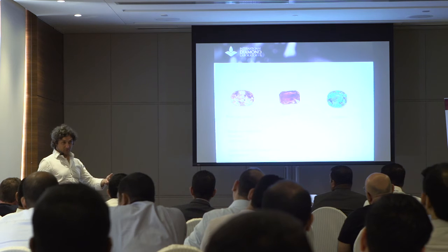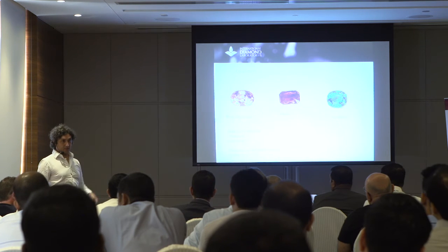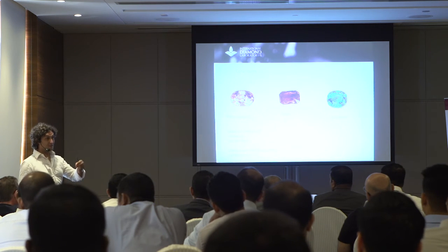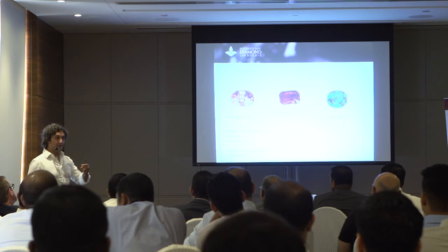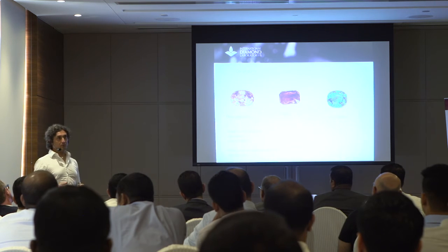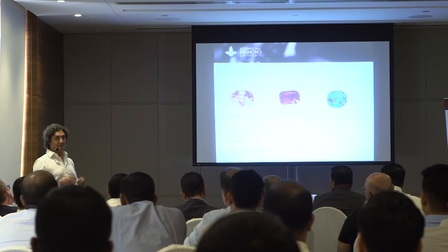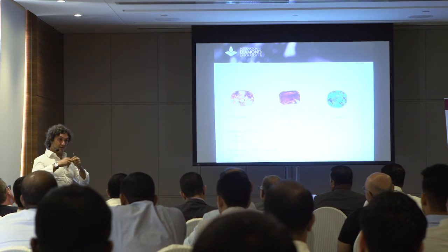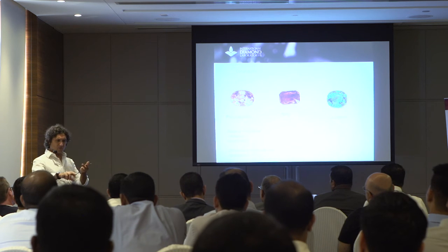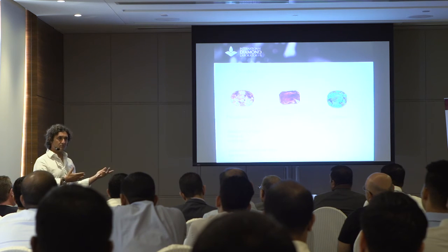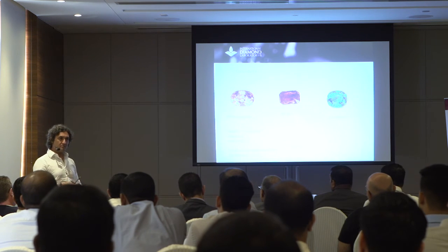They are more stable, they will last. The problem with oil was that it was coming out. Some stories, people traveling on a plane, difference of pressure, and the oil comes out. And then on the stone, you see, oh, now there is a crack. There was no crack before, because it becomes visible.